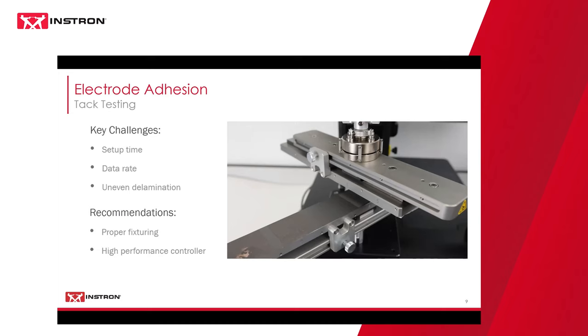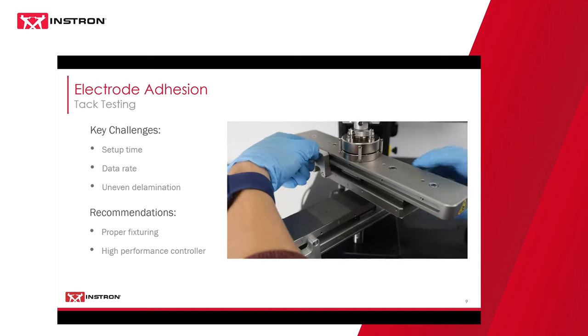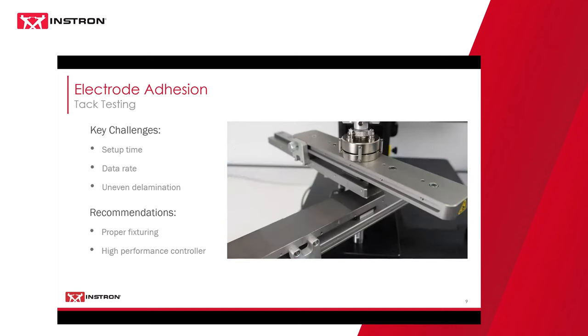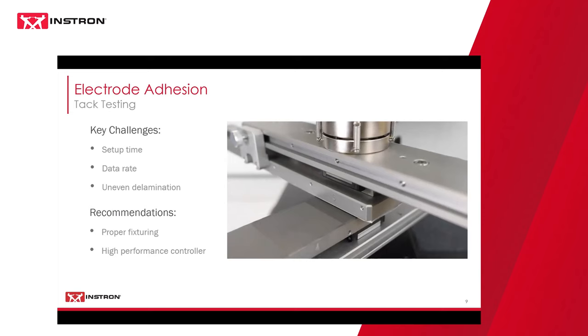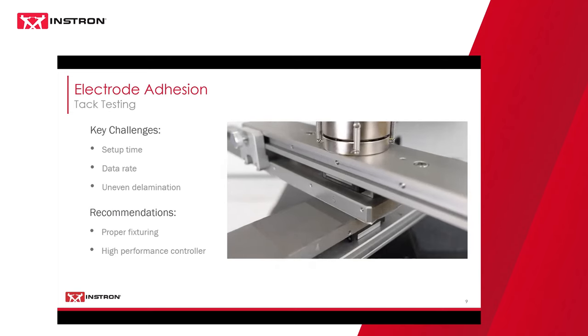The fixturing to the right here is an example of a tack fixture that Instron has designed. It's designed to test 5 specimens consecutively, all from one single larger specimen. The fixturing ensures proper contact area and alignment of every single test. Let me play a quick video for you guys here. So this is just showing it moving over to the next specimen. That would be, I believe, specimen 5, coming down, and this is an abbreviated, quickened version of the test just to show as an example here.